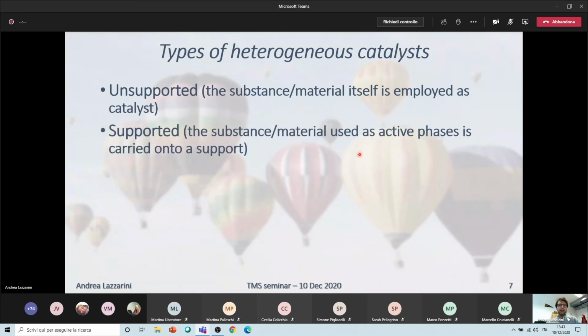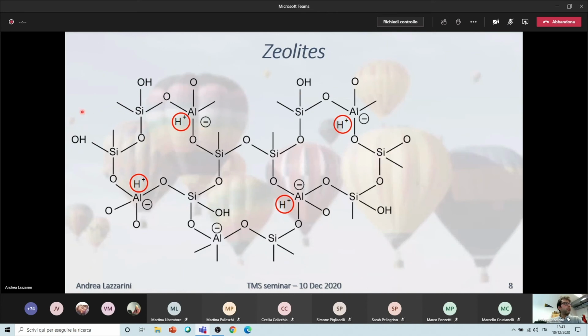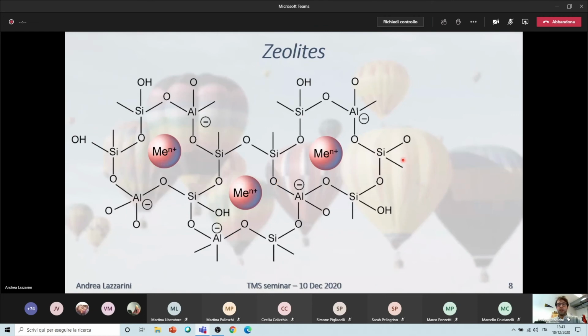Apart from zeolites that can be unsupported, we have supported catalysts. This means that the support that we are employing is not the material that is active in the catalysis. And again, one of the more famous examples of these supported catalysts can be zeolites, because as I told you before, they naturally present a proton to counterbalance the relative negative charge inside the lattice, but it can be easily exchanged with metal ions that can act as redox catalysts. So the zeolite itself, that was bearing the proton and so being itself the catalyst, now is an active support that is able to capture and trap these metal cations that can perform redox catalysis.